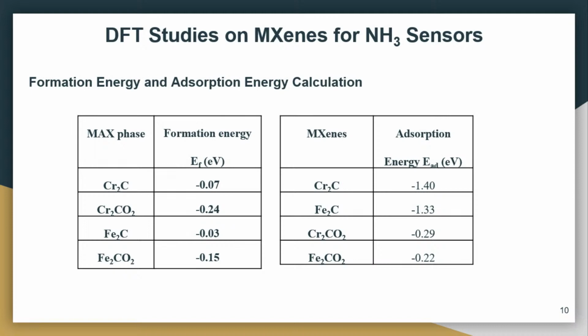So we concluded from the adsorption energy, the Bader charge analysis and the charge transfer interactions that Cr2C can have a higher adsorption, and can act as a sensor for NH3, right? And yeah, this is what we observed from this paper.